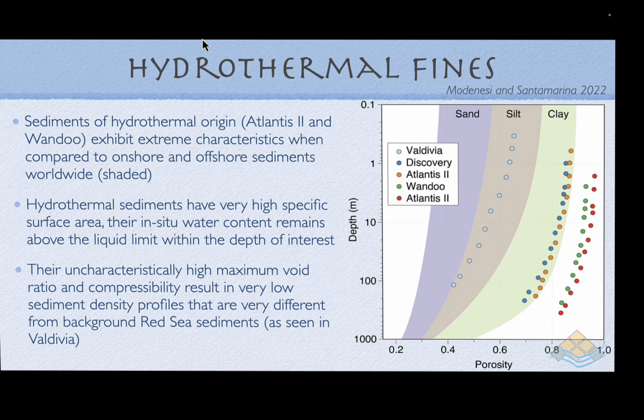There's another interesting aspect of the sedimentology. If we look at the grain size as reflected in porosity in these hydrothermal sediments, the Atlantis II Deeps and also the Wandoo for that matter are ultra-fine sediments. On the right-hand side of the standard plot fields for deep oceanic sediments, which are plotted for sands, silts and clays for oceanic sediments worldwide, we can see that in terms of depth to porosity, the Atlantis sediments are very fine-grained, very high surface areas, and accordingly very high levels of retention of fluid in the pores in that sediment. These hydrothermal sediments exhibit what we could call extreme characteristics if we compare them to the typical onshore and offshore sediments worldwide, as indicated by the three shaded fields for sand, silt and clay.